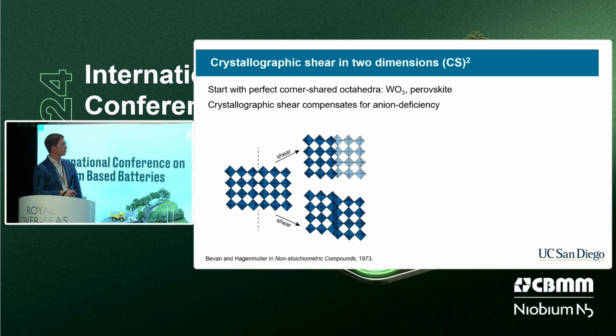The problem is if you use this structure, and it's been tried many times before, without any kind of modification, it collapses because lithium is not held well in this structure, and so it undergoes distortions and twisting modes that basically clamp down on the lithium and then prevent you from having good transport properties after you insert even a relatively small quantity of lithium.